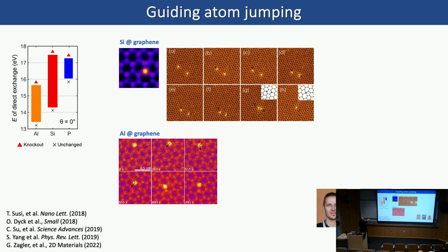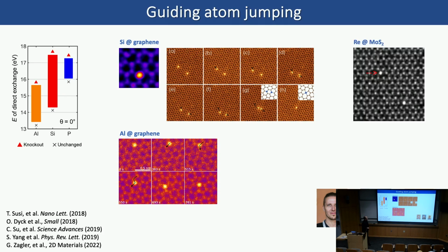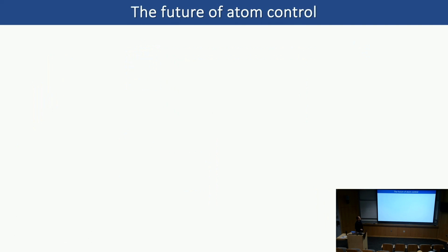By using the same idea, you could just guide the silicon atom to jump around a hexagonal ring of graphene and let it jump across those 6 different sites. And this also applies to aluminum in graphene, and in some cases, it also applies to a dopant in MoS2. So that's how we got atom jump.